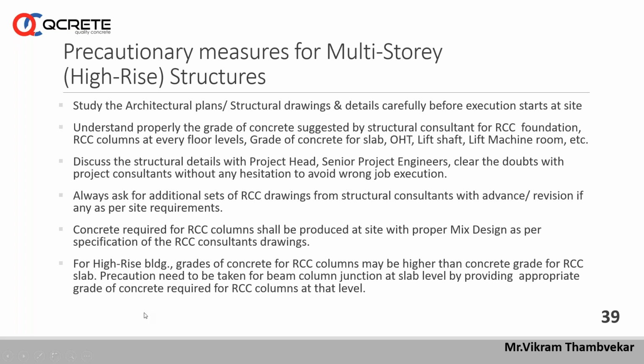Secondly, for a high-rise building, the grade of concrete for an RCC column may be higher than the concrete grade of the RCC slab. Precaution needs to be taken for the beam column junction at slab level by providing the appropriate grade of concrete required for the RCC column at that level. Generally, suppose your grade of concrete for column is M40 or M50 and grade of slab is M30 or M40, generally M30. People don't order M40 in a small quantity to cast the column junction first and then a different grade of concrete, say M30, for casting the slab. They place only one grade of concrete for casting the slab, and that beam and column junction gets filled with a lower grade of concrete than the concrete suggested for RCC columns.